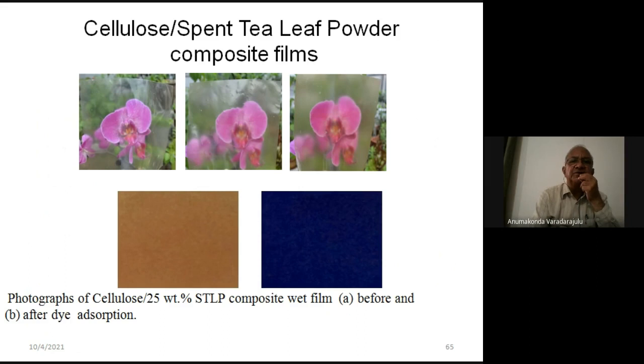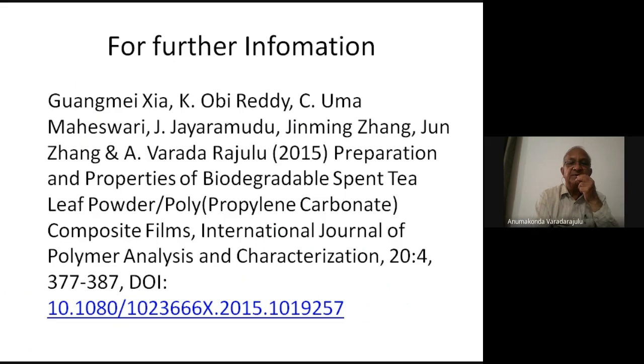Then we used this in the cellulose matrix and made the films here. And this can be used as a packaging material. We found an additional application for this composite film with this spent tea leaf powder, because the tea leaf powder has the ability to absorb the dyes. So for example, here we used methylene blue. We dipped this film in methylene blue solution, and we have seen that the entire methylene blue dye was taken up by this film. So this can be used for the purification of industrial wastewater where the dyes are used. For further information, you can go through this particular publication here.